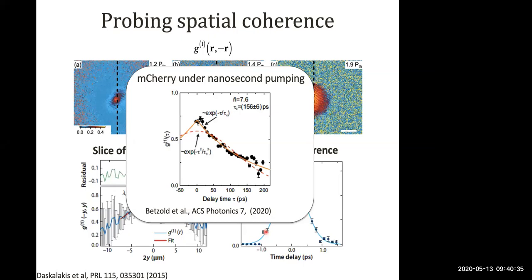Recently, so actually just this year, there was work from the group of Sven Höfling using nanosecond pumping. So now the pump duration is no longer impulsive, but much longer than the relaxation dynamics in the system. So you can probe the intrinsic condensate coherence time. And they found that coherence time in this microcavity based on a protein called mCherry was as much as 156 picoseconds. So this is very interesting because it also allows you to do quasi-CW type of experiments.